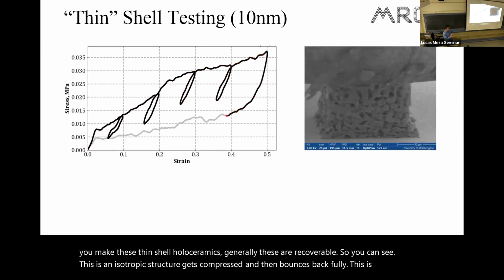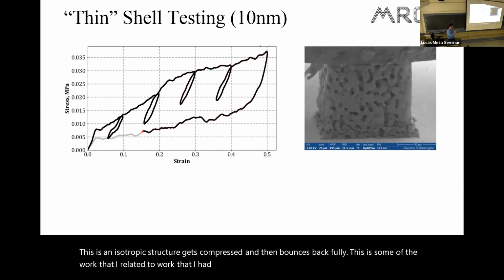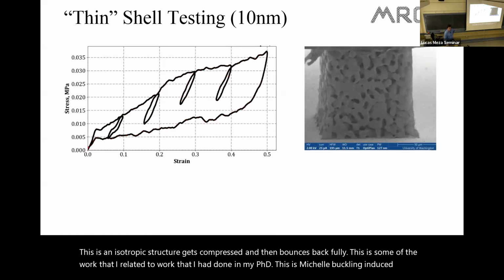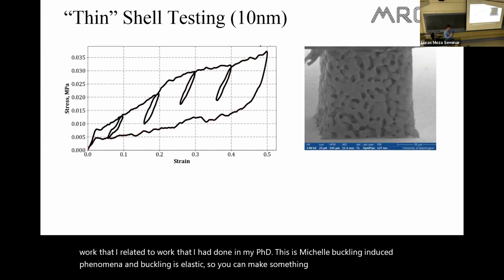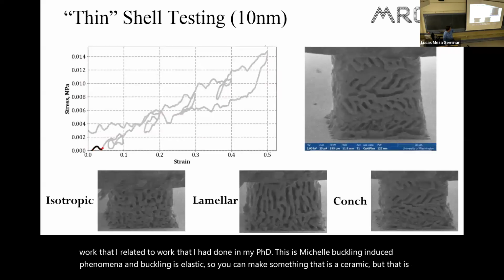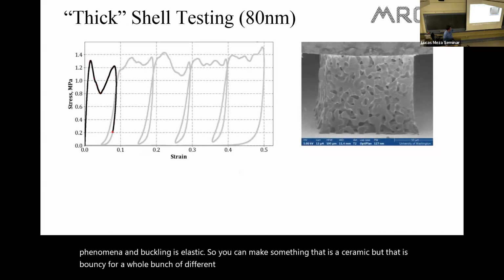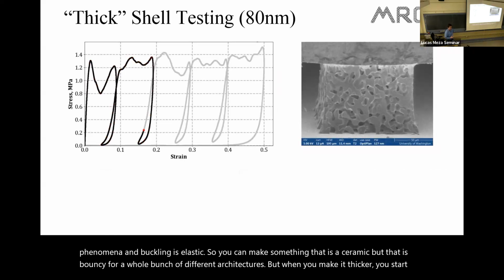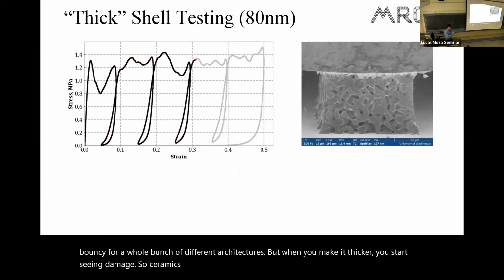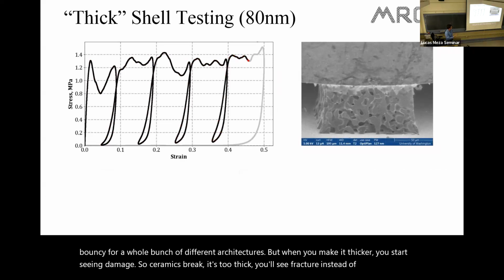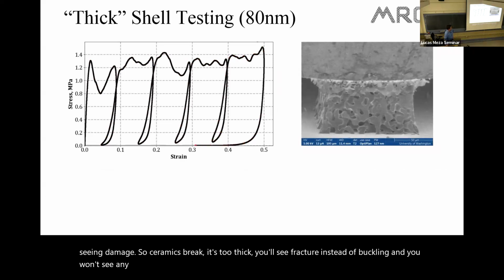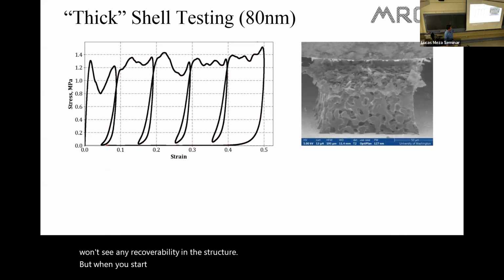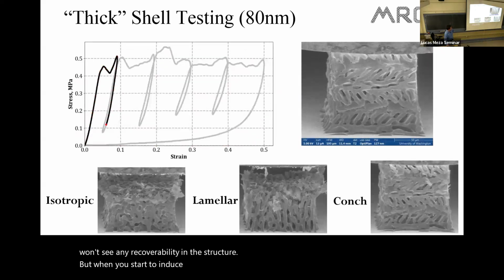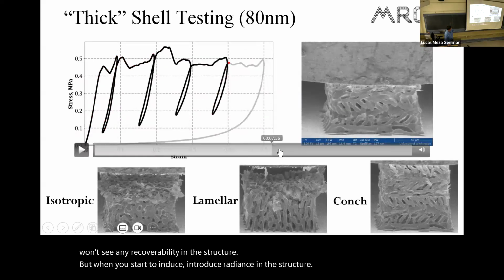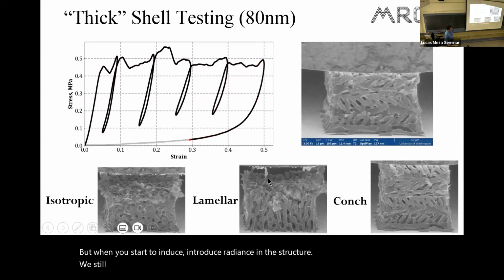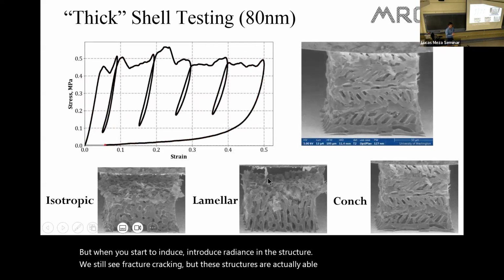This is related to work that I'd done in my PhD. This is the shell buckling induced phenomena, and buckling is elastic. So you can make something that is a ceramic, but that is bouncy, for a whole bunch of different architectures. But when you make it thicker, you start seeing damage. So ceramics break. If it gets too thick, you'll see fracture instead of buckling, and you won't see any recoverability in the structure. But when you start to introduce gradients in the structure, we still see fracture, cracking, but these structures are actually able to fully recover.